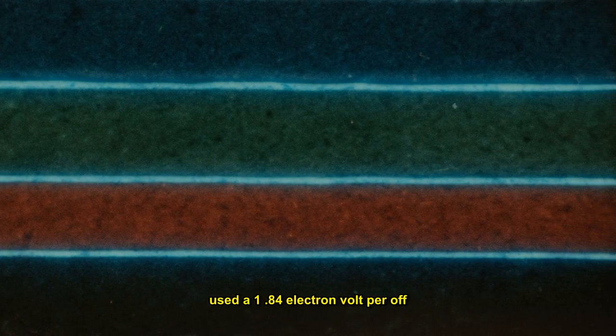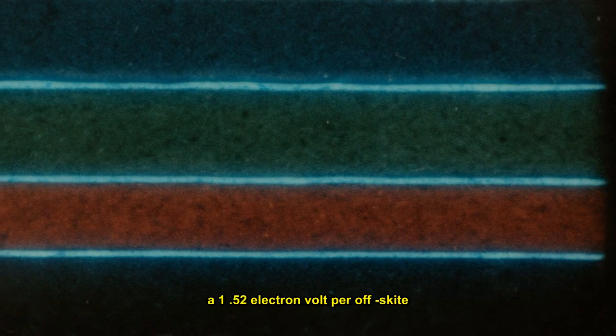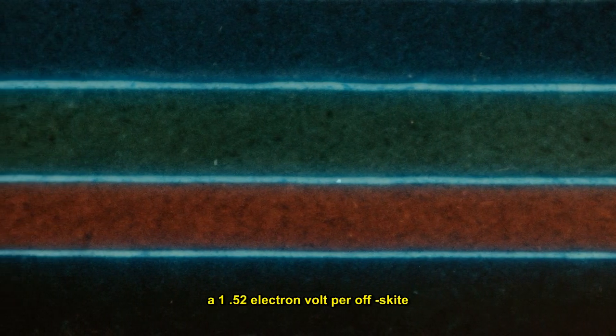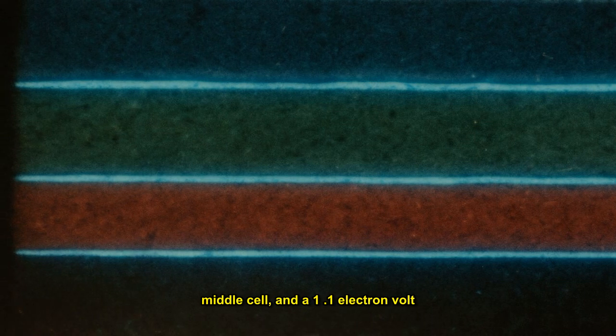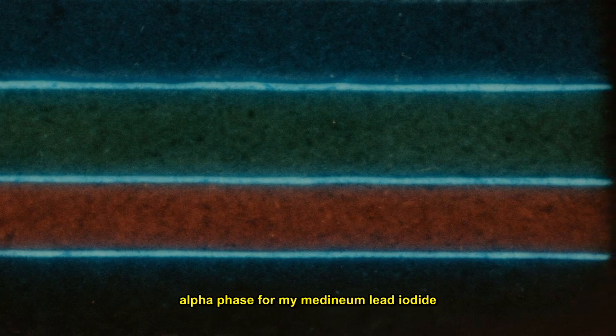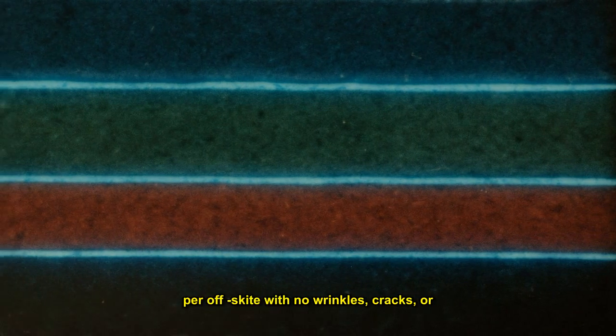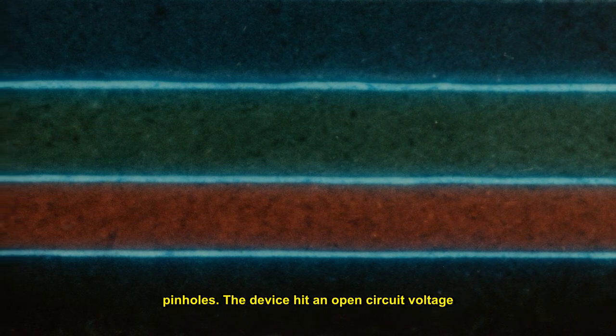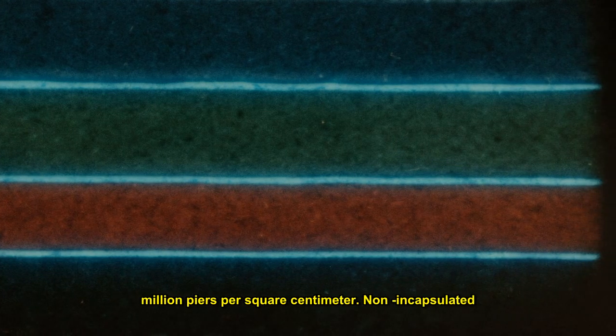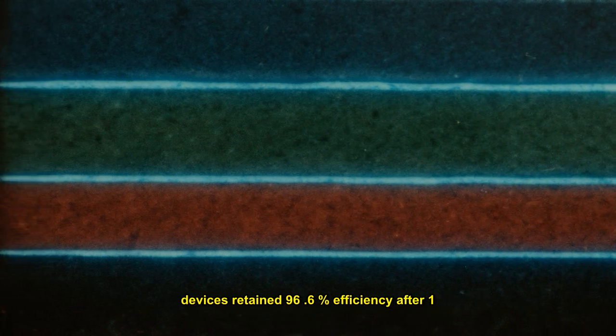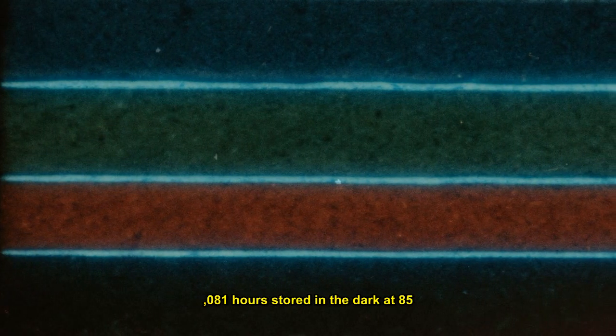The stack used a 1.84 electron volt perovskite top cell, a 1.52 electron volt perovskite middle cell, and a 1.1 electron volt silicon bottom cell. The middle cell was the breakthrough, requiring stable alpha phase formamidinium lead iodide perovskite with no wrinkles, cracks, or pinholes. The device hit an open circuit voltage of 2.84 volts and short circuit current of 11.6 milliamperes per square centimeter. Non-encapsulated devices retained 96.6% efficiency after 1,081 hours stored in the dark at 85 degrees Celsius.